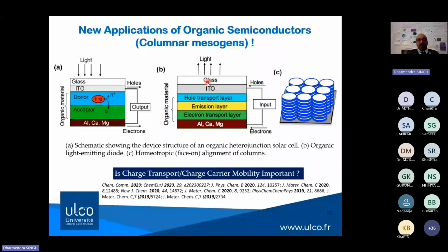So obviously there is a particular compulsion to orient the columnar materials. If you want to fabricate an organic photovoltaic device or OLED device, you have to orient your disc-like molecules completely perpendicular to the substrate. And the charge carrier mobility of this compound is very important in these devices, because the efficiency of these devices will depend on the interfacial conditions and the charge carrier mobility of these molecules.